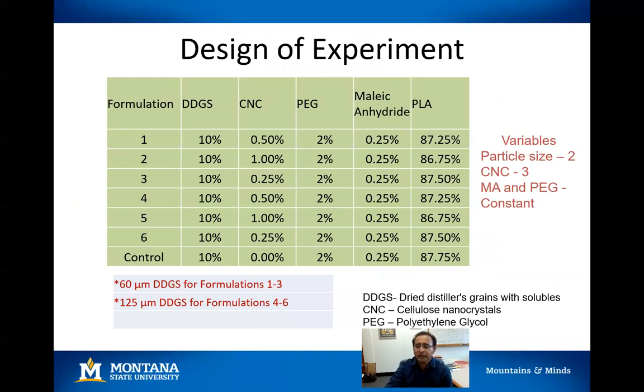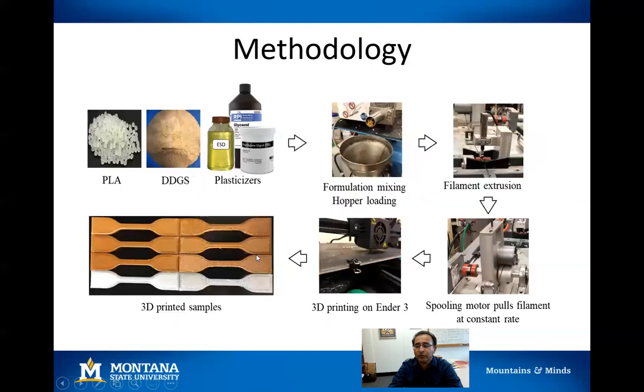The design of experiment included 5 materials: DDGS, that was constant at 10%, PEG was constant at 2%, and the coupling agent, again, constant at 0.25%. And the two materials that we varied were the CNC and the polylactic acid. The CNC percentage varied from 0.25% by weight all the way to 1%, and the polylactic acid amount varied through these formulations. I want to mention another thing: we used two different particle sizes of DDGS. So formulations 1, 2, 3 used 60 micrometer DDGS, and formulations 4 through 6 used 125 micrometer DDGS particles. And the control was no cellulose crystals in the formulation.